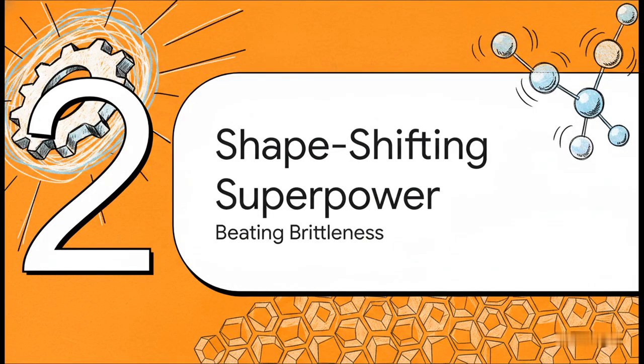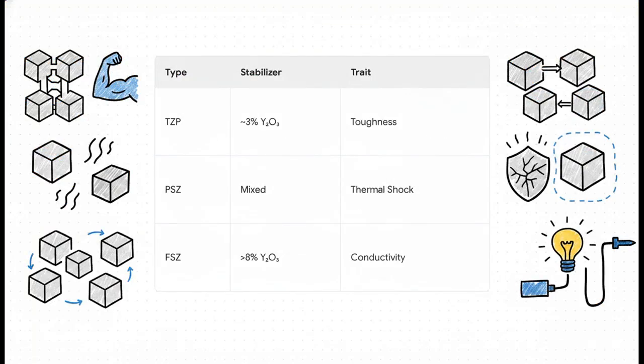That brings us to section 2, the shape-shifting superpower. This is how it beats brittleness. You see, depending on exactly how much of that stabilizer we add to the mix, we get totally different identities for the material. If we add just a tiny bit of yttria, like around 3 mol%, we get TZP, or tetragonal zirconia polycrystal. This stuff is ultra-fine-grained and has absolutely massive toughness. But if we use a bit more of a stabilizer, say magnesia, we get PSZ, which stands for partially stabilized zirconia. This one mixes cubic and tetragonal phases to give you extreme resistance to thermal shock.